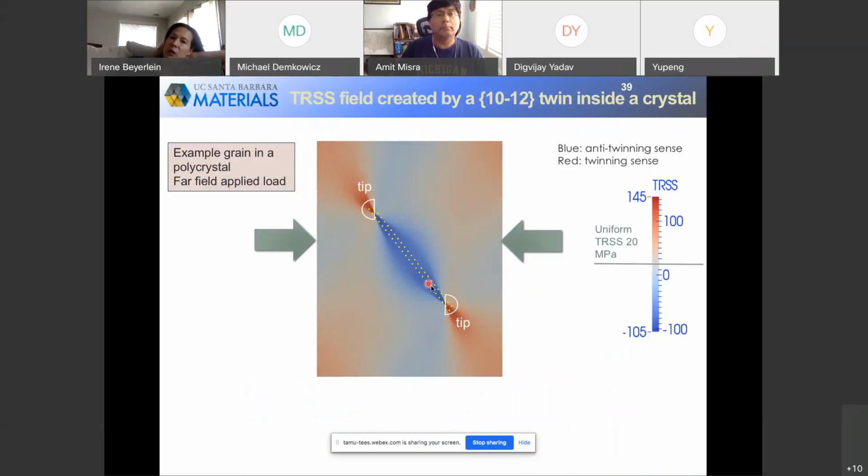As far as the reorientation part, that changes the orientation of that domain with respect to the load, which then could favor different types of slip. You could imagine you would get a softening if the new slip that was invoked is softer than the one prior to that.